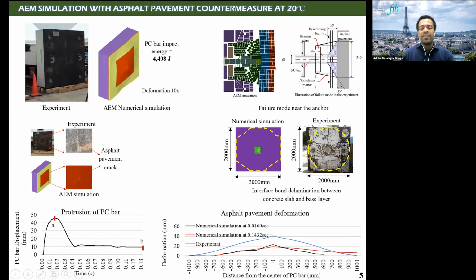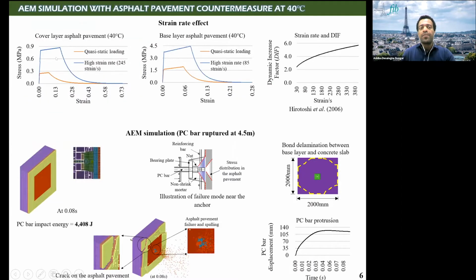So you can clearly see that the deformation is maximum near the center of the specimen, and it's decreasing toward the edge of the specimen. So this one is AEM simulation with asphalt pavement at 40 degrees centigrade. At 20 degrees centigrade, it works, but what about at 40? Because the asphalt pavement performance is decreasing with increasing temperature.